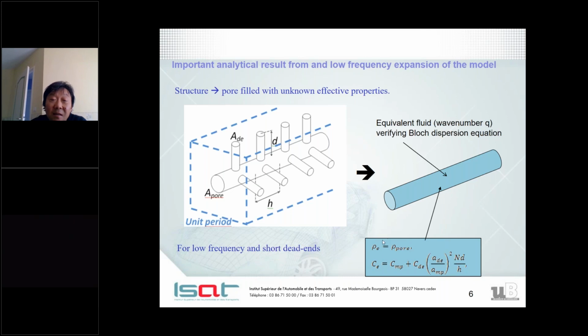So the effective density of the fluid with dead ends is the same as the density of the main pore without, which has some importance, because as we will see in our model, we have a tortuosity of 1, which is different from what probably Keith will present. But in our study, the important result is on the fluid compressibility, the air compressibility. The equivalent compressibility is given by that of the main pore without dead ends, plus the contribution of the periodically distributed dead end pores.